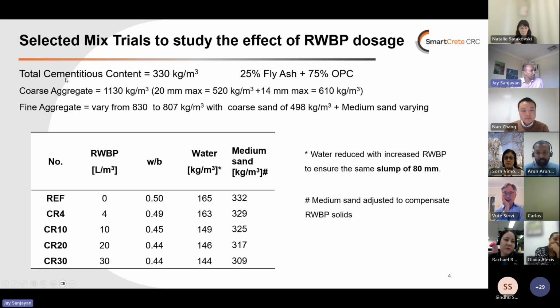And you can see at the top the cement content is about 330, which is a typical concrete. It's got 25% fly ash, coarse aggregate about 1130 with 20 millimeter and 14 millimeter aggregate, and fine aggregate.